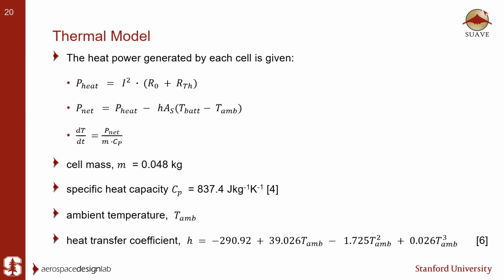The thermal model, secondly, is a simple thermal model which uses the square of the current times the total resistances, and the heat generated can be used to determine the net power produced by the system, which comprises the heat generation through resistance heating, as well as the heat loss from convective heat transfer. Here, the cell mass was the mass of the 18650 cell, or the small cylindrical cells, which was 48 grams. The specific heat capacity, taken from literature, was around 837 joules per kilogram per Kelvin.